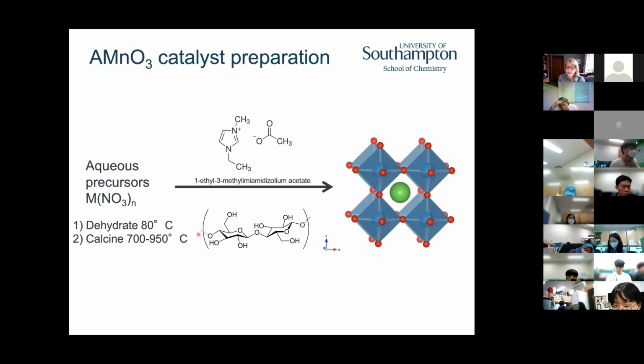So we wanted to study these materials, and the problem is people have done a lot of thin film work, but that's not very good for the way I do experiments. So I need a particle material. And for most of them, the synthesis is by a sol gel route, and that gives you really big particles, and then you just don't see anything. Or a co-precipitation route.